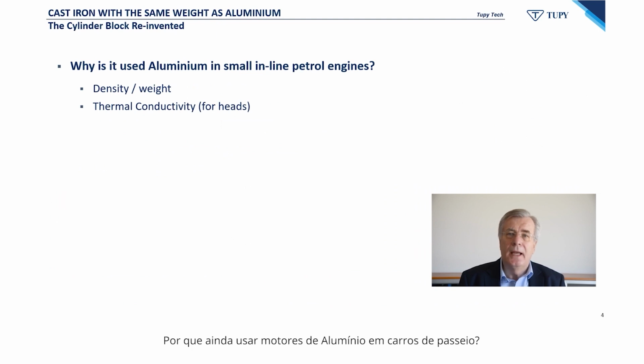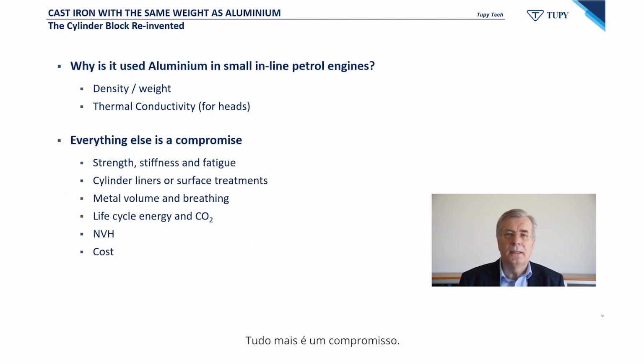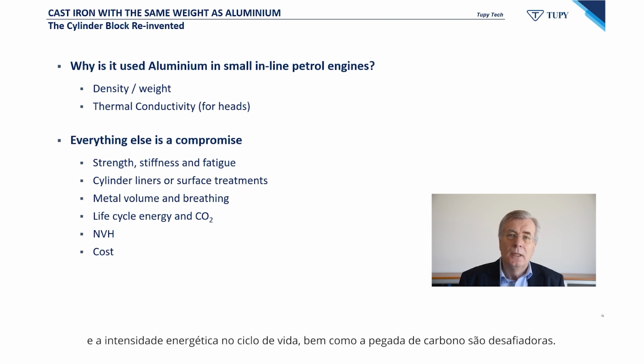Why do we still use aluminium engines in passenger cars? Okay, the density and weight of aluminium is attractive, and we have a relatively good thermal conductivity, and this is especially interesting for cylinder heads. Everything else is a compromise. Strength, stiffness and fatigue is limited. We need cylinder liners or surface treatment. The metal volume must be large and so the breathing areas are limited. And the life cycle energy and CO2 footprint for aluminium is challenging. The NVH behavior is limited and we have cost issues.